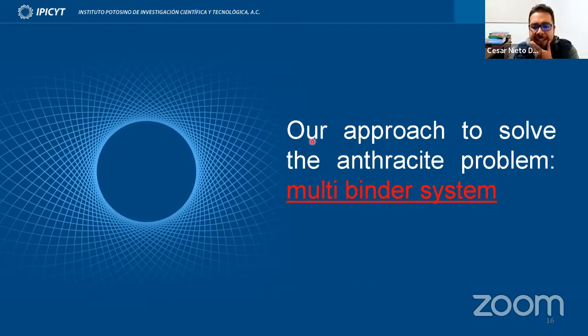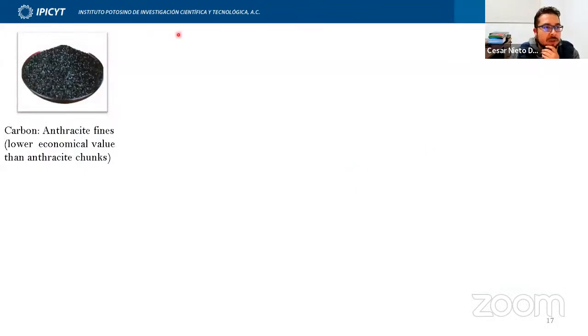Essentially what we did at that time to solve this problem is that instead of using just one binder that usually just burns at very high temperatures inside the furnace, we use multi-binder systems. This multi-binder system was designed to provide strength to the anthracite briquette at different temperatures inside the cupola furnace. First we start with carbon anthracite fines. The anthracite fines in the US are a low value carbon. When they are mining anthracite, they just discard the very small particles. We took those small particles and used them to produce the anthracite briquette.